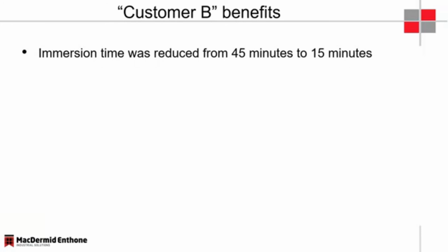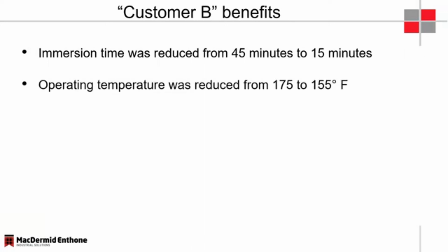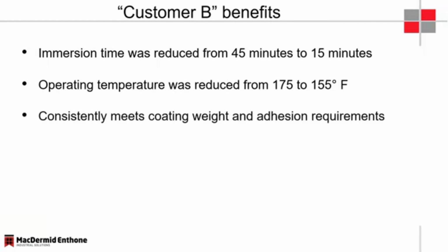So they have sustained the reduced immersion time. The previous immersion time, again, had been 45 minutes. We've reduced that to 15 minutes. And that additional 30 minutes over the course of a year represents a lot of additional productive time for the customer. In addition, they've been able to sustain a reduced temperature. Their previous process operated at 175 Fahrenheit. We've dropped that to 155. So again, this 20-degree differential over the course of a year represents additional cost savings.